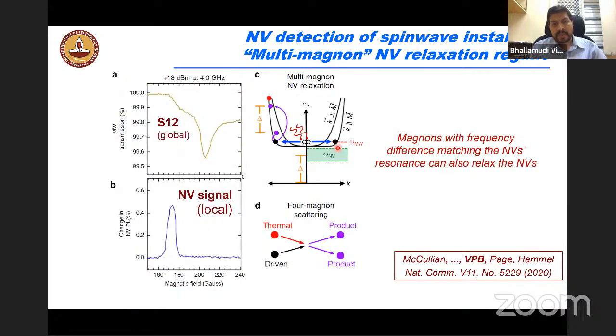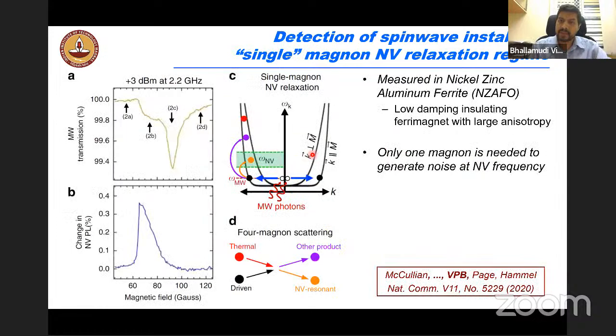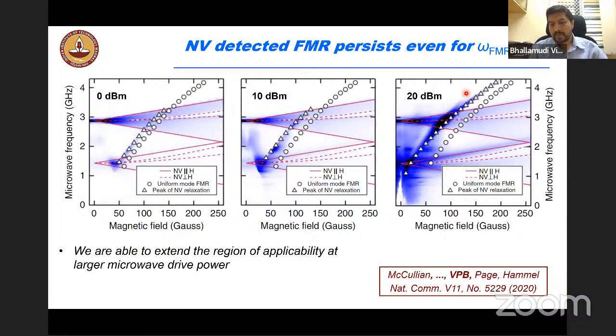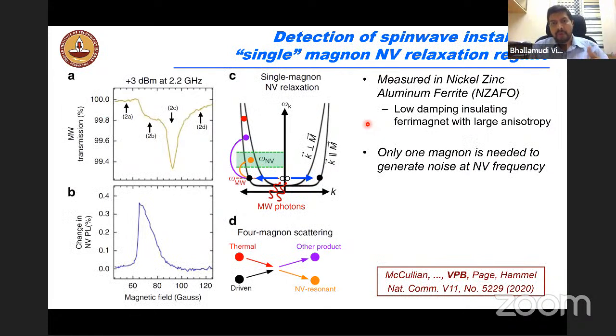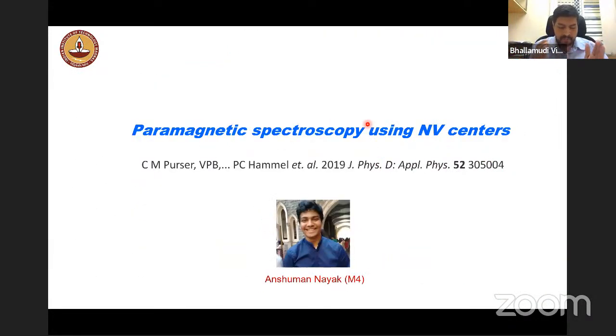But the other way we can also see is that when you cross this ferromagnetic gap here, so let's say the NV was sitting in this gap here, you could still have a process, a four-magnon process, where the thermal wave and the driven wave are creating two magnons. And the difference of these magnons now can match the NV centers. And that again can relax the NV centers and give us the spectral signature for the ferromagnetic resonance that you can measure here. So the short thing that I would summarize there is that we have been able to measure FMR, and we are finding ways of extending the range of doing this FMR spectroscopy.